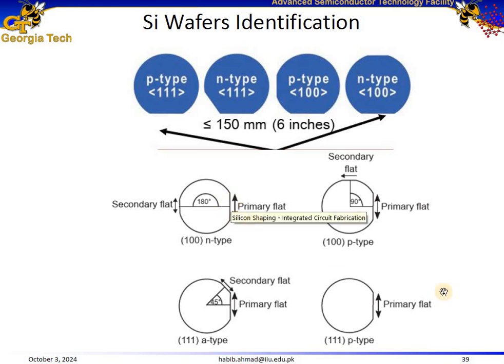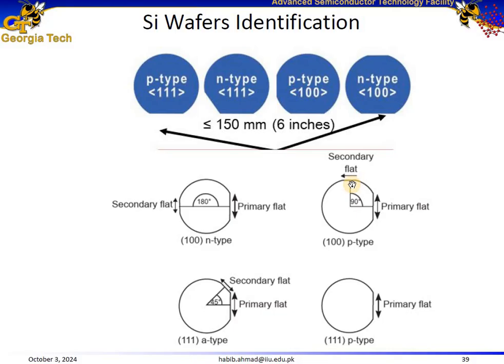Similarly in this image, the primary flats are indicated on the right side, and the secondary flats are like these ones over here. The primary flats are bigger; the secondary flats are smaller. The primary flat is the largest flat on the wafer and helps indicate the wafer's crystal orientation. The secondary flat is smaller and helps identify the doping type — n-type or p-type.